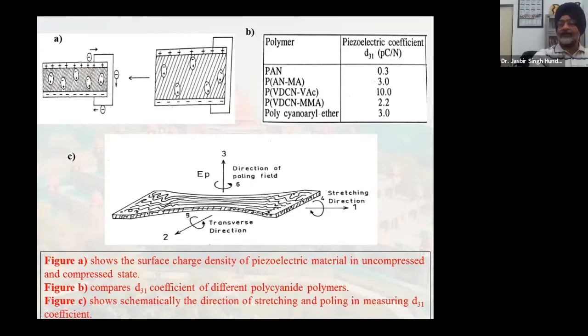Now, what is this D31, and what do the 3 and 1 indicate? Look here. This is a film that is stretched. This stretching direction is labeled as 1, and if the field is applied perpendicular to the stretching direction, that is 3. When we measure the piezoelectric coefficient, not only during poling, we stretch the film in direction 1, along the length, and we measure the charges along direction 3. The surface charges that change, the piezoelectric current that flows, is measured along direction 3. So that's why D31.